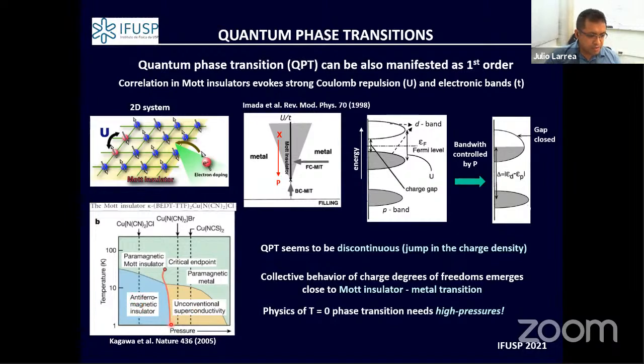But if you follow and increase the temperature, taking measurements at many points, what you see is a sharp transition defining a first order transition that terminates at the critical point for the Mott Insulator. So in this case, looking at the correlations in the electron degrees of freedom, what you see is that for the Mott Insulator, apparently the quantum phase transition is discontinuous.